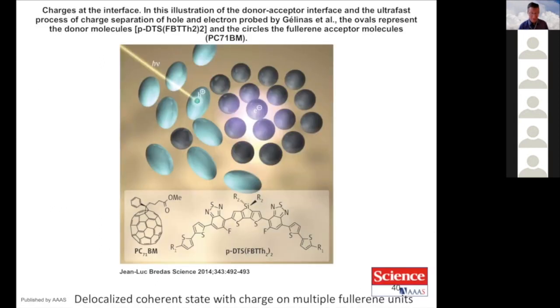properties. By using laser spectroscopy, people have shown that upon excitation of these donor molecules in green, a charge is generated that is delocalized over multiple acceptor units. So this negative charge, it's not localized just on one buckyball molecule, but over several. So they did it with the Stark effect. It's a complex method, but correlates with what I just showed you on the X-ray diffraction. The radical anion, it's delocalized over several fullerene units in what they call a coherent state. The electronic wave function of the radical anion, it's delocalized.